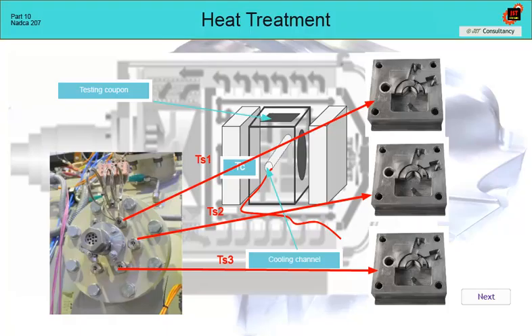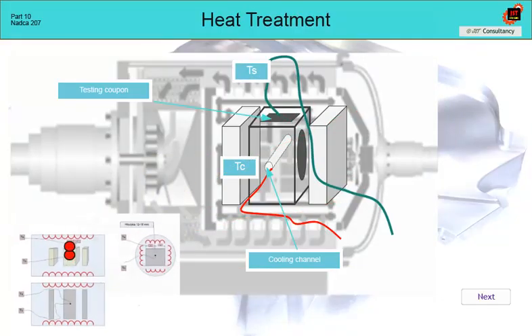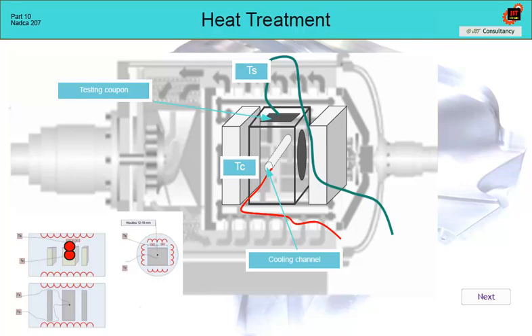However, if we have a furnace equipped with only 2 batch thermocouples and we want to harden several inserts simultaneously, we place both TS and TC thermocouples in the same largest insert in terms of heating. The individual inserts must have similar characteristic dimensions so that the smallest ones do not exceed the austenitization time set as a maximum of 90 minutes from reaching the required temperature at TS. From the point of view of cooling rate control, the record for the largest insert with placed thermocouples is then evaluated, and for the other, smaller inserts, it is assumed that it was faster than the recorded one.